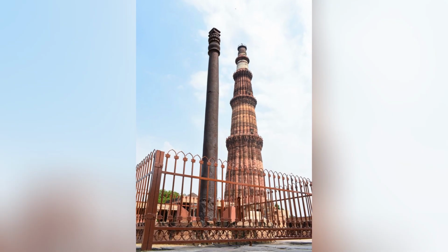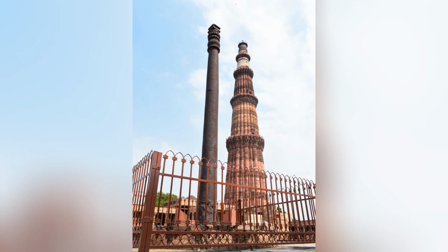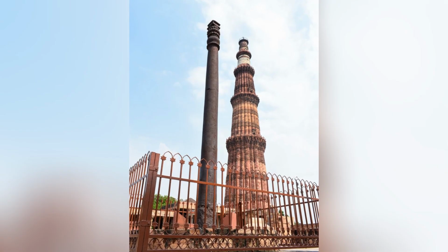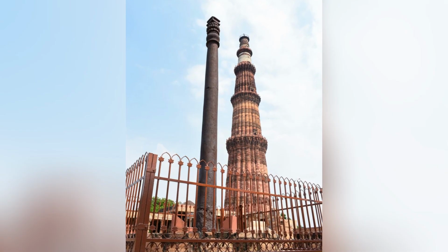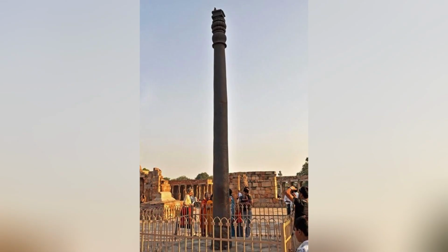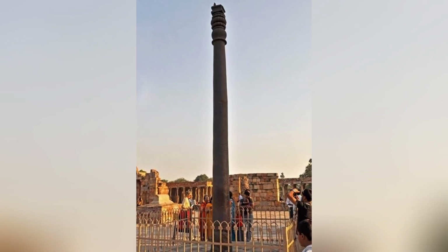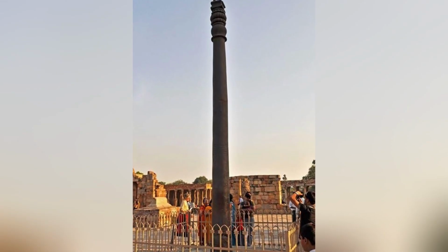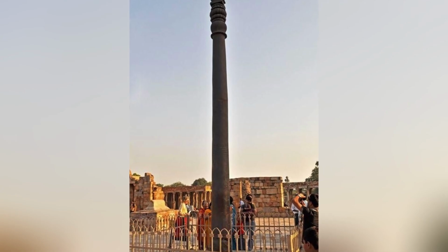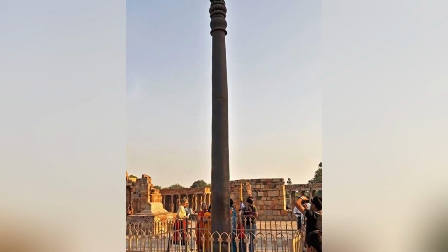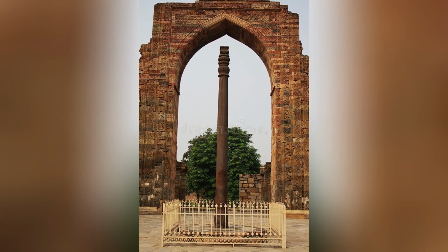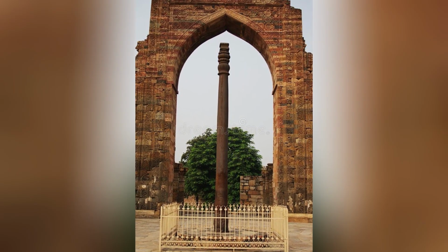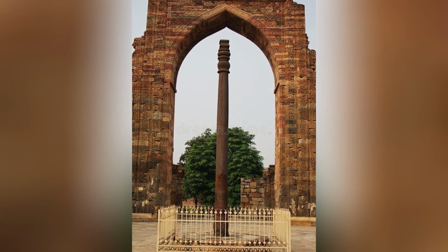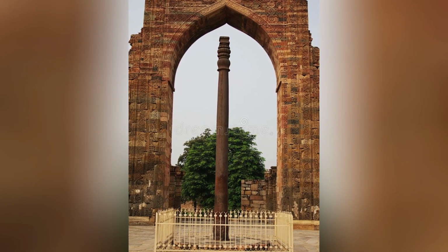The comparison between the Delhi pillar and other iron objects that have been exposed to different climatic conditions provides additional evidence for the importance of climate in the corrosion resistance of phosphorus-rich iron. Iron objects from coastal regions where the humidity is continuously high and where the air contains dissolved salt show significantly more corrosion than inland objects, even when the iron has a similarly high phosphorus content.